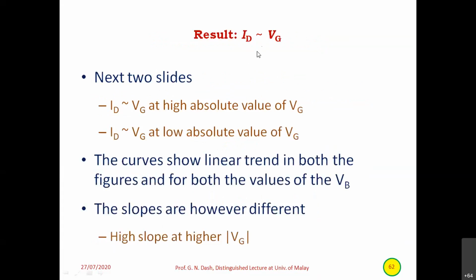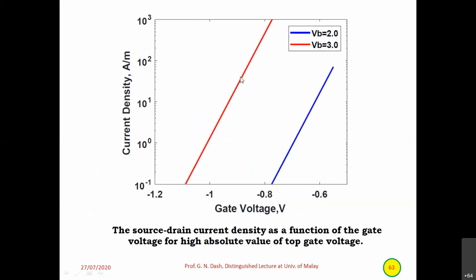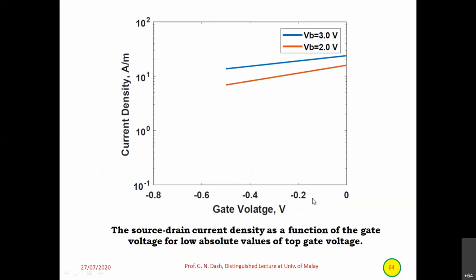The next two slides will show these graphs, ID versus VG at high absolute value of VG, and ID versus VG at low absolute value. The curve should show a linear trend in both figures and for both values of VB. The slopes are, however, different: high slope at higher VG and low slope at lower VG. This is the slope of the straight line, and the slope is high at higher absolute value. This is a lower absolute value of gate voltage, and this slope is relatively small.